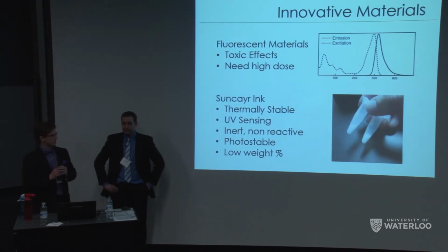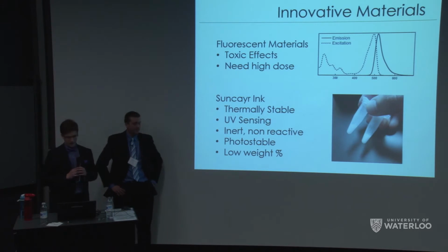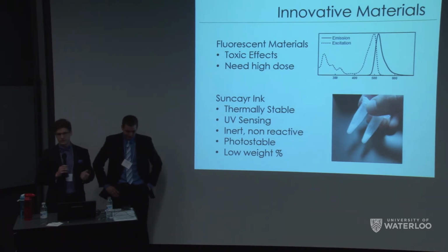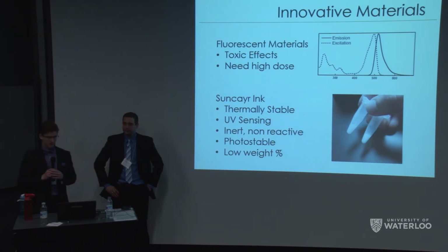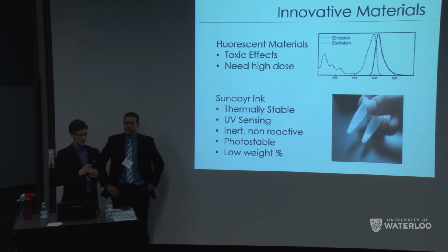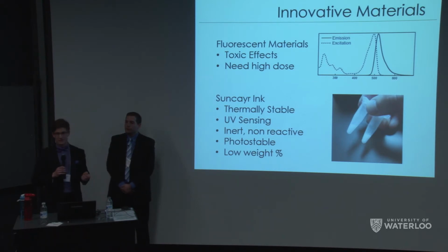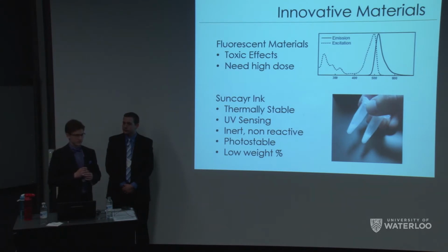So, fluorescent materials have a large absorbance in the visible light range. So even when you're not exposed to UV light, you can see the color in the fluorescent material. And even the most fluorescent materials like fluorescein still show this effect. The only absorbance they have in the UV range is in the UVB, which you only ever get exposed to on very bright days with no clouds in the sky. So for our design, because you can still get sunburned pretty badly even on a cloudy day, it doesn't make sense for us to use a fluorescent material.